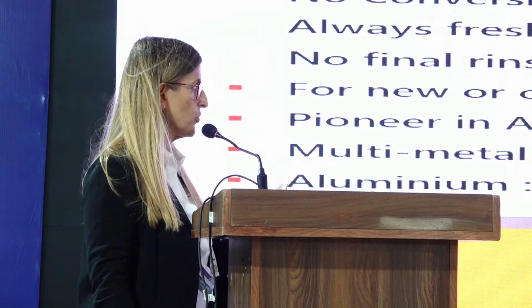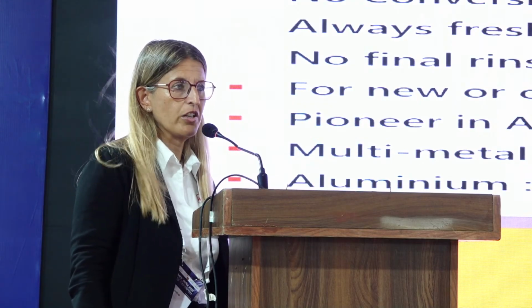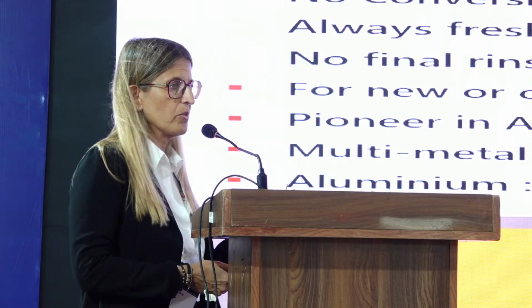We have more than 100 units installed and working perfectly. And as I told you, it can be an option for all the customers that want to switch from a Chrome 6 technology to a non-Chrome 6 technology with a minimum investment, because it's really easy to install and it doesn't really require any modification in the line, because it goes directly at the end of the line. This is the setup of what is needed. It's only a couple of pumps in order to mix the products, and then you create this mist.